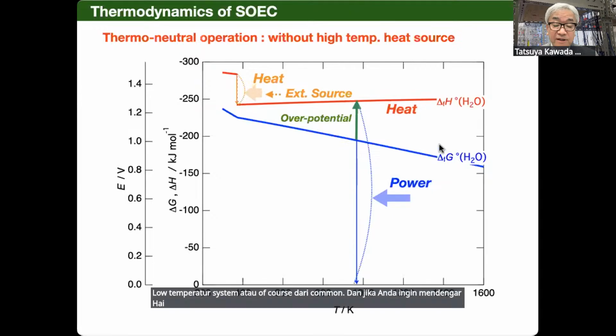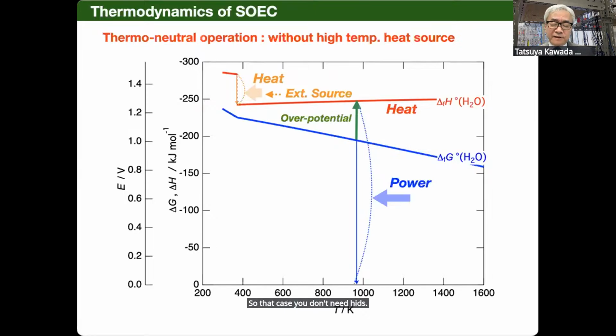But of course, a high temperature heat source is not very common. And if you can't find that kind of high temperature heat source, you can generate that heat by its overpotential. Yeah, you need some overpotential anyway. So if your overpotential is tuned to go to the enthalpy, then this system can be operated in a thermal neutral situation. So in that case, you don't need external heat, because heat generated by the overpotential can be used to maintain its temperature. In this case, of course, you still need some external source for making steam from the liquid water.